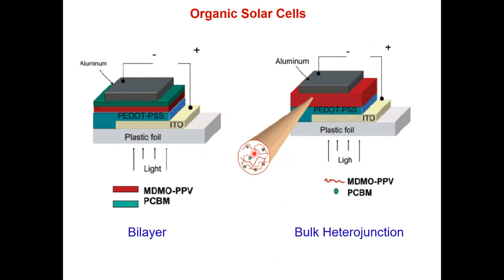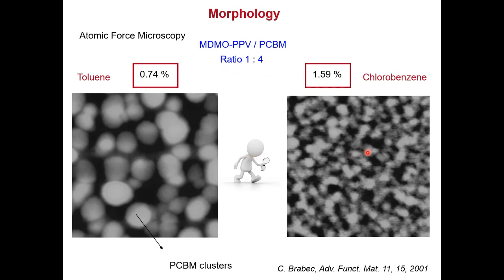But this is very tricky to make the right morphology because it's something kinetic, and you want to find the right condition. You can play with the solvent, the concentration, the temperature. So it's very, very tricky to find the right composition. And here a very useful tool is atomic force microscopy, because when you make the blends, you can go with this microscope and you can probe the surface, of course, but you can probe and distinguish the two components.